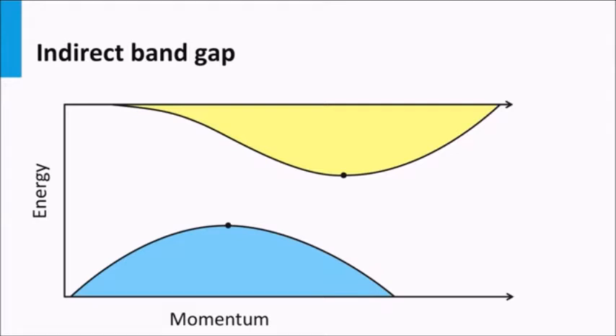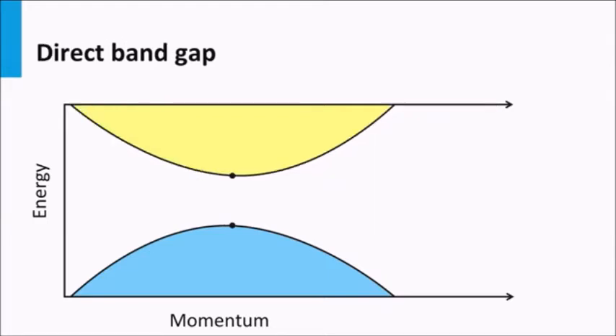For an indirect band gap, the highest point of the valence band is not aligned with the lowest point of the conduction band. This means that exciting an electron from the valence to conduction band requires energy provided by a photon and momentum provided by a phonon. In contrast, a direct band gap has the highest point of the valence band vertically aligned with the lowest point of the conduction band in the energy momentum space. This means that exciting an electron from the valence to conduction band requires only the energy provided by a photon without any additional momentum transfer.